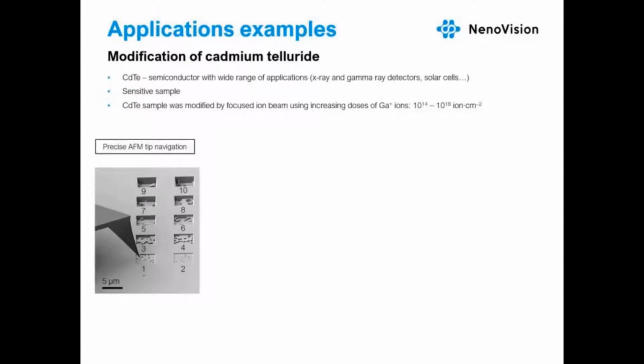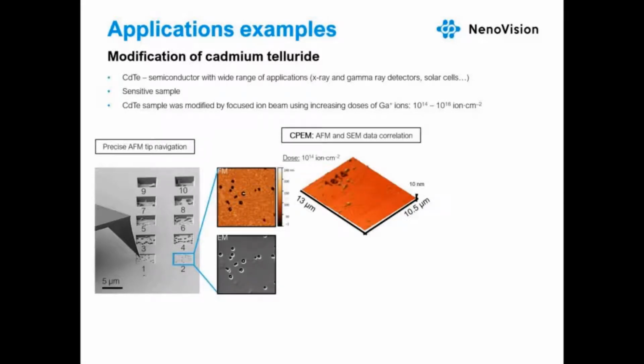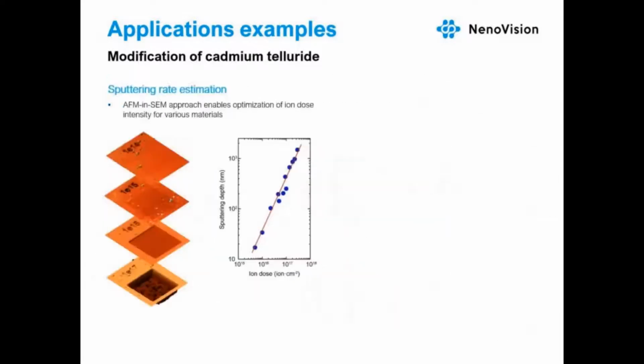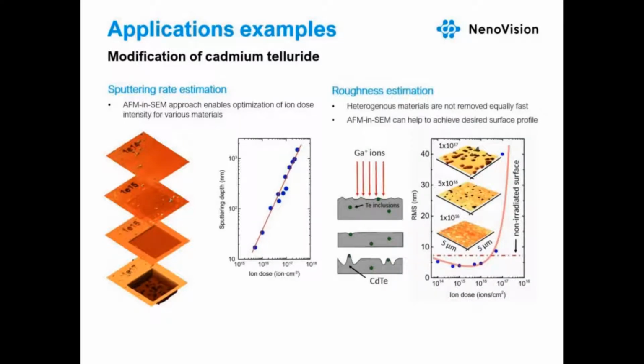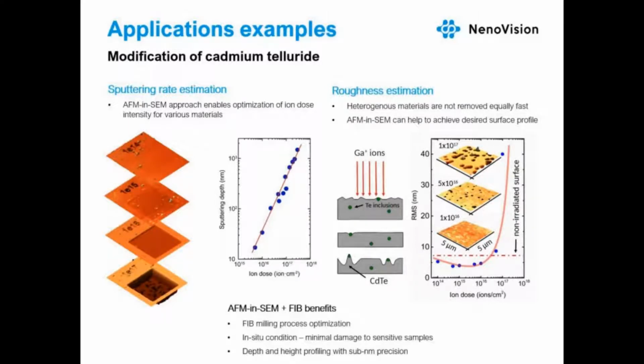Another example nicely shows how the combination of AFM with SEM equipped with focused ion beam can be utilized to optimize the focused ion beam milling process. So for this purpose, cadmium telluride was sputtered using increasing doses of ions as depicted in the SEM image. And each of these 10 frames were immediately analyzed by AFM and SEM in in-situ conditions, and the data were correlated and used to optimize the ion dose intensity. And because cadmium telluride represents a heterogeneous material, the AFM topography can be used to achieve the desired surface profile. And of course, since the complete analysis is done in in-situ conditions, this can be used even for sensitive samples such as cadmium telluride.